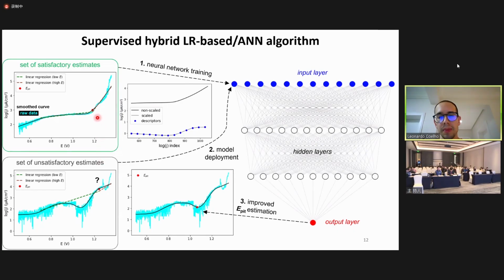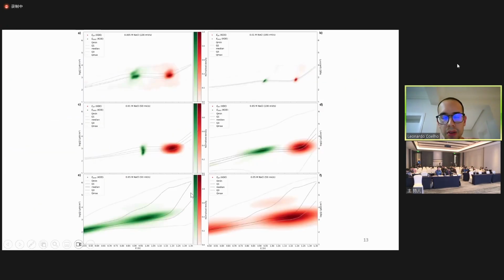So we developed this algorithm, and we trained a neural network to understand how this point was estimated, and we used the remaining 20% of the data that we call bad estimates, right? The ones where the points were not good because, for one reason or another, curves were more complex. And the neural network has done a very good job in finding the points that we were looking for. And after that, we were able to plot the pitting potential distribution displayed in red, but not only that, we used the same type of model for estimating the passive potential, which is the potential width where we get into a plateau. The current that we measure is really constant as a function of the applied potential.